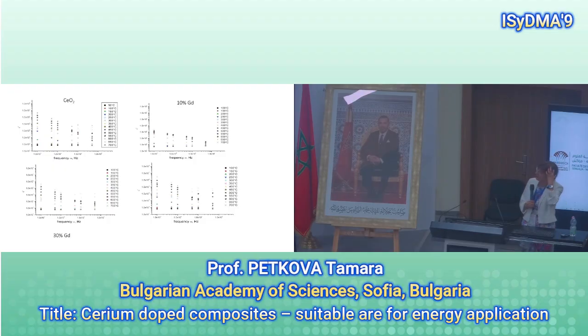At the end of our study, we performed some electrical measurements. Here are shown the results from these measurements, which we performed using impedance spectroscopy. The data for the real part of the electrical permittivity are shown on these figures, and we found that the values decrease by orders of magnitude when the amount of gadolinium is increased. Obviously, the values decrease also with the frequency of the investigation.